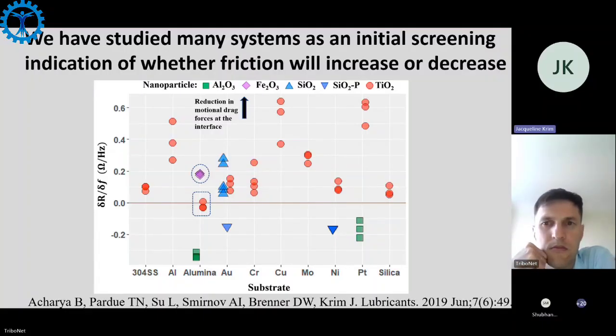And the other thing we noticed about this was the range of properties of all these things we've looked at: silica, platinum, nickel, alumina. They had many properties from insulator to electrical conductor. And the properties of the nanoparticles are the most consistent. They dominate the system. Electrical properties, in particular, of the combination of the macroscale and nanoparticles, start to really dominate. Okay, next slide.